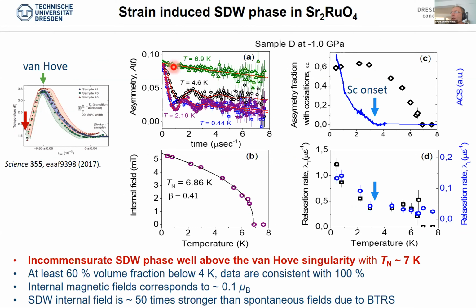And here you see the time spectra in the μSR experiment at high temperature slowly relaxing, this is as usual. But then below 7 Kelvin, you see the clear development of coherent oscillations of the muon spins. And that means we develop static magnetic order with a large internal magnetic field. And so the internal magnetic field turns out to be now in the order of, at low temperatures, here is the magnetic field as a function of temperature. It's about 5 millitesla. That means 50 Gauss. So it's definitely a factor of 50 times stronger than any magnetic field which we have seen in the time reversal symmetry breaking superconducting state. Is there still superconductivity?